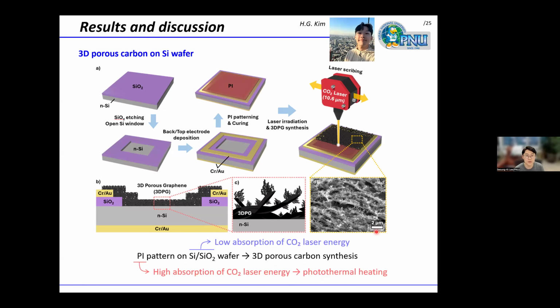Next, I will introduce another research topic from our group, which involved the direct synthesis of porous carbon supports on the silicon semiconductor wafer. As shown in this figure, instead of using the conventional PI film, we use a photo-patternable polyimide material. So through the photolithography process, we define the area of this polyimide film on the silicon wafer. And then when a CO2 laser is irradiated here, only the polyimide layer is selectively converted into porous graphene. So here also the key point is using the different absorption property between the polyimide and the bottom substrate. The polyimide has high absorption of this CO2 laser, but silicon oxide and silicon let that laser beam penetrate.